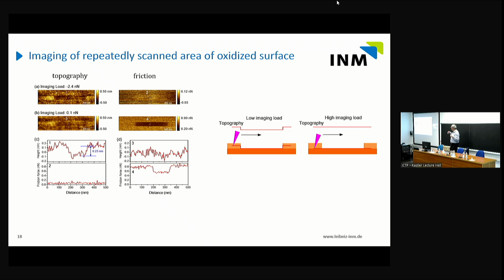What we can do also is, after removing the outer layer, image at a little bit higher load. That is the second panel from top. And then you see hardly anything in topography, but you see actually a great friction contrast. So friction is lower where we had already removed the outer layer. So it's pretty delicate because you practically can never image without changing the surface.